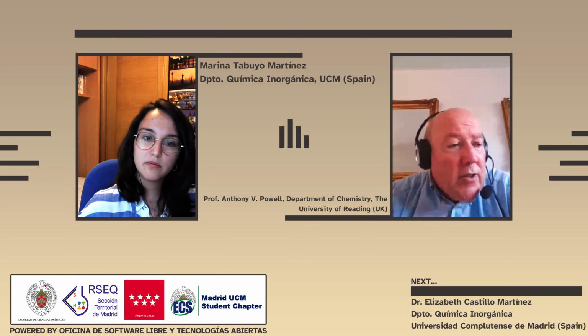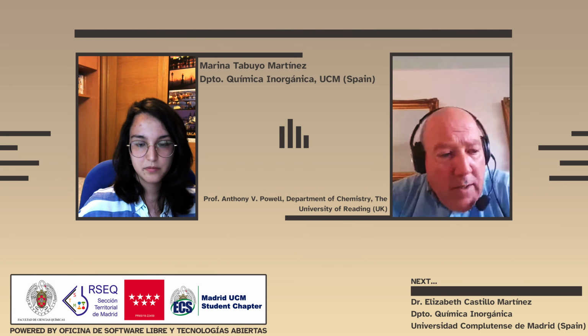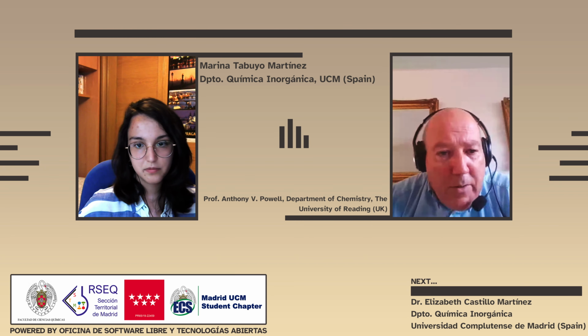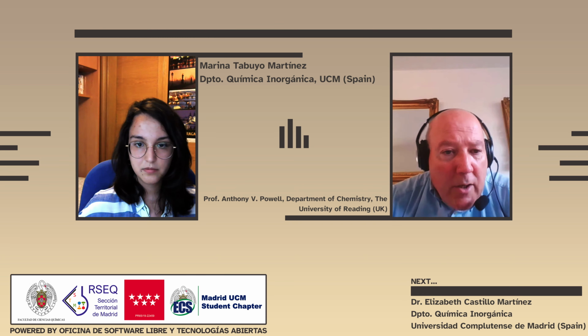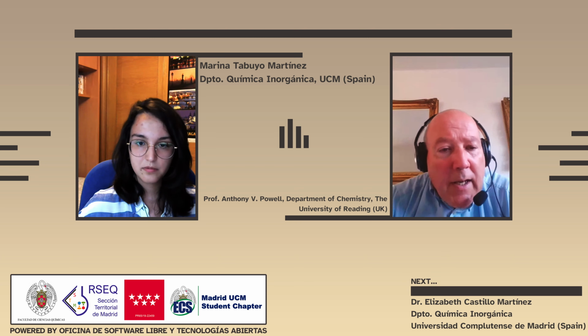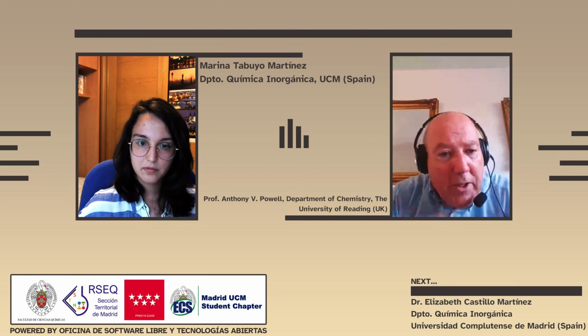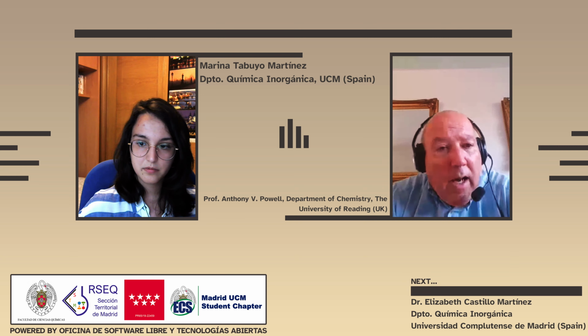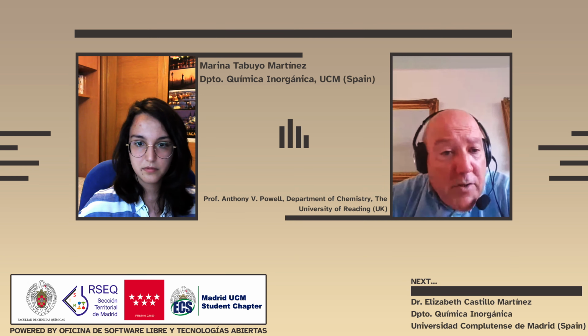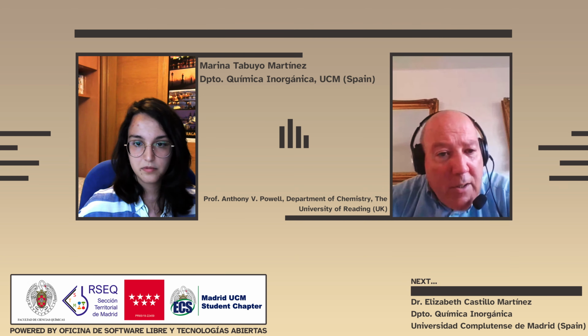Yes, we do. I didn't show it in the interest of time, but as well as those individual Raman spectra that I showed, we've also done Raman mapping of the surface of the composite. So we make the composite, we press a pellet, we then map the surface with Raman spectroscopy, which shows up the different carbonaceous regions. And those regions are actually very evenly distributed. I think it's because we're going down to that colloidal level when we do the mixing that we can get good homogeneous mixing there.